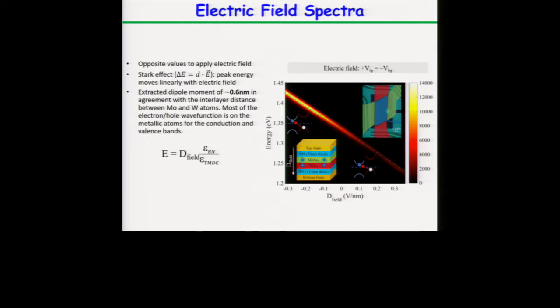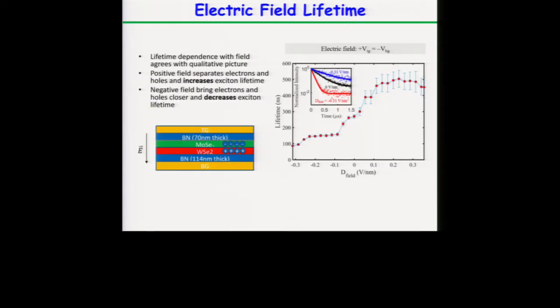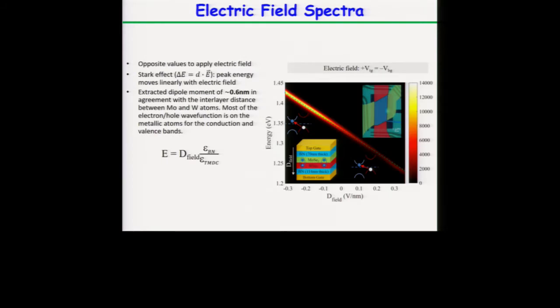We also see that the intensity changes with the electric field, and the lifetime also changes. For zero displacement field, the lifetime is around 250 nanoseconds, but we can increase it up to around 500 nanoseconds. We're doubling the lifetime of these interlayer excitons with electric field. As I mentioned, a positive electric field is stretching the separation between the electron and hole pair. I forgot to mention that the slope of the energy versus displacement field gives us a dipole moment of around 0.6 nanometers, and that's the separation between the metals of these two layers, which is mainly where the wave function is present.